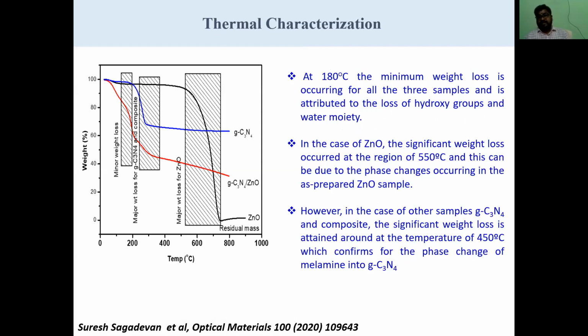And for thermal characterization, you can see that the pre-sample decomposed at 180 degrees Celsius, with a minimum weight loss occurring at the pre-sample, attributed to the loss of hydroxy groups and water moiety. In the case of zinc oxide, the significant weight loss occurred in the region of 550 degrees Celsius, which can be due to phase changes occurring in the prepared zinc oxide sample. And for the other sample, graphitic carbon nitride, in red color, the weight loss is attained around 450 degrees Celsius, which confirms the phase change of melamine to graphitic carbon nitride.